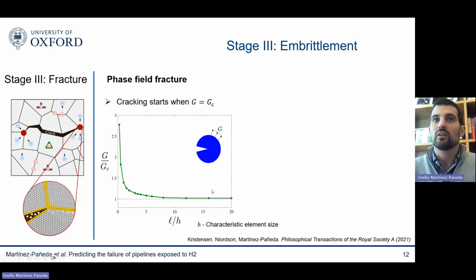mesh independent. This is good because there are a lot of models out there which are mesh dependent, which means that one engineer sitting next to another is going to get different results using the same parameters. This is different. Here, as you can see, H is the characteristic element length. As you refine your mesh, eventually you get the same behavior. So your mesh has to be fine enough.